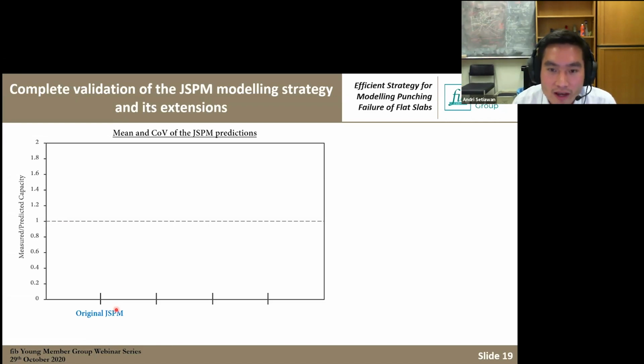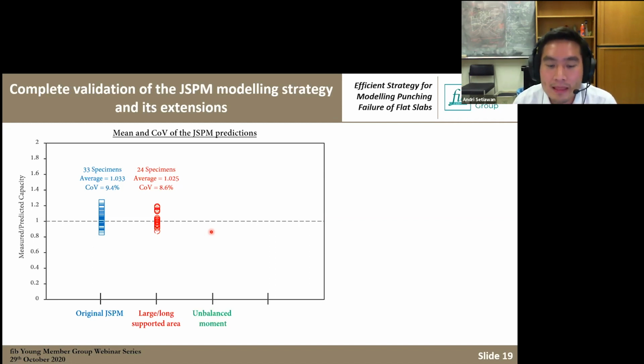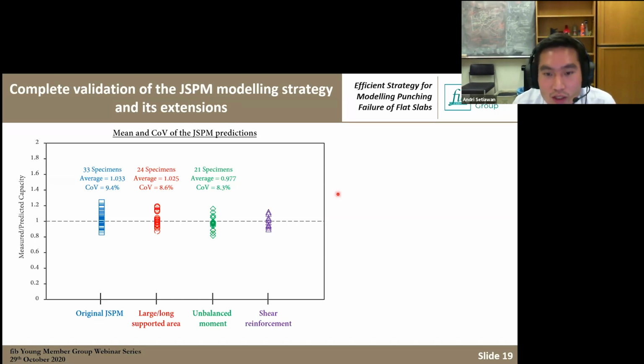For the original JSPM, which is the initial verification, we did 33 specimens with average of 1.033 and variation of 9.4%. The second scenario is with large loaded support area. We simulated 24 specimens with the average of 1.025 and variation of 8.6%. And the slabs with unbalanced moment, both with monotonic and cyclic, we simulated 21 specimens. The average is 0.977 and the variation is 8.3%. And lastly, for the slabs with shear reinforcement, continuous and isolated, we simulated 12 specimens with average of 1.006 and variation of 7.3%. So we are really satisfied with the model because the average is very close to 1 and the variation is less than 10%.